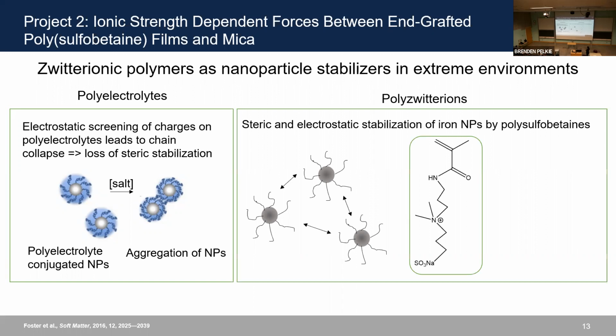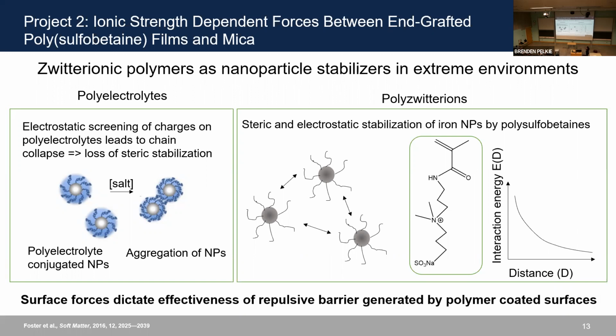In this work, using a small amount of polysulfobetaine to decorate the surfaces of iron oxide nanoparticles, it was shown that they can be sterically and electrostatically stabilized. So if we plot the interaction energy of the particles as a function of distance, then we see that it is a purely repulsive curve. With decreasing distance, the interaction energy increases. So surface forces are very important, and they determine how effectively the repulsive barriers will be generated by polymer-coated substrates.